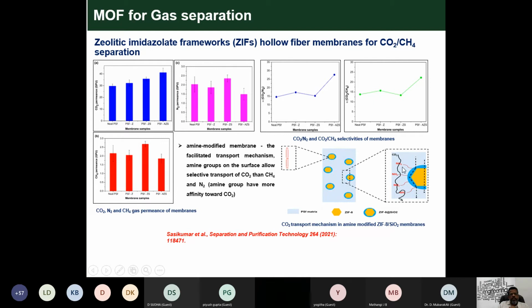See the NH2 and the CO2. The NH2 is attached between the nano gap, due to the functionalization of the amine modified membranes. The amine modified membranes are responsible for transport of carbon dioxide through the membranes in the nano gap.